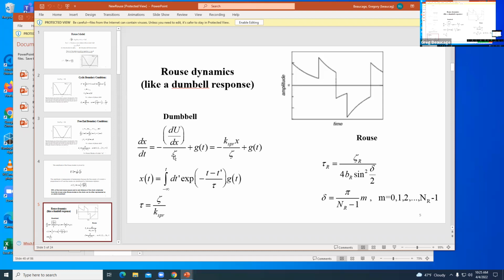And in Langevin, you divide by the friction factor, and this G(t) just becomes like an instantaneous velocity caused by temperature. Randomly, the things are moving around. So you have this pulsation going up and down randomly, and then you have a decay back to the zero point, the average position. So the Rouse becomes the same as a dumbbell. The only thing you really get out of that analysis is a molecular weight dependence of the tau and of the viscosity, right? But the physics of how it behaves is exactly like a dumbbell, the simplest possible dynamic system. Single relaxation time, where the relaxation time is the viscosity divided by the modulus. So it ends up being just the simplest thing.